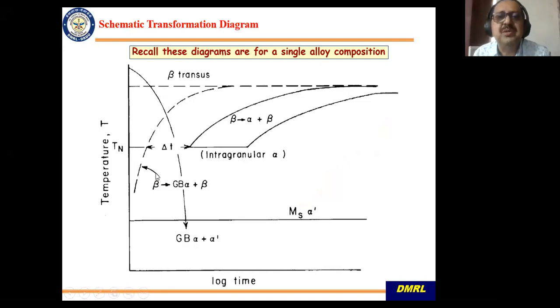Now coming to titanium alpha plus beta alloys and beta alloys, they also have time temperature transformation curves, and it looks like this. The first curve is for formation of grain boundary alpha. As I was telling you, grain boundary alpha forms first because that's a high energy area, the grain boundary, and alpha likes to precipitate there. The first thing when you cool alloys, either alpha plus beta or beta alloys, from above the beta transus, it hits this line.